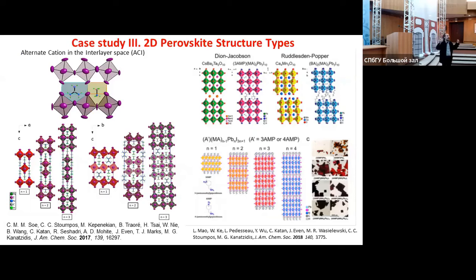You can change the offsets of the layers. For example, in the original case I showed you, the two perovskite layers are offset by half an octahedron, so that this octahedron fits exactly in this pocket. Other types, like for example the Dion-Jacobson type, where you use a 2+ cation, not two monocations, but a 2+ cation, so you can bring the layers closer together, one on top of the other.